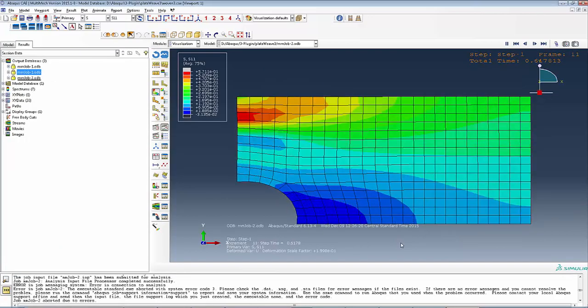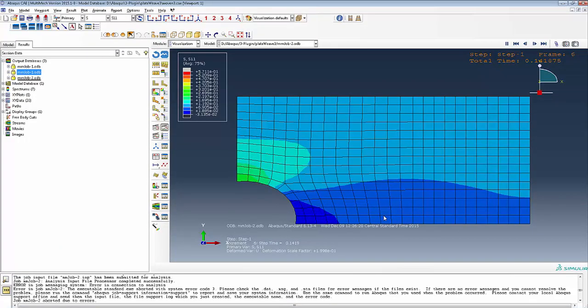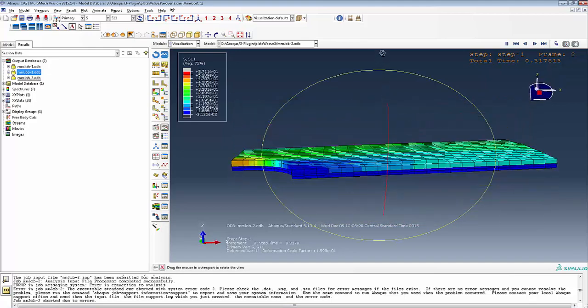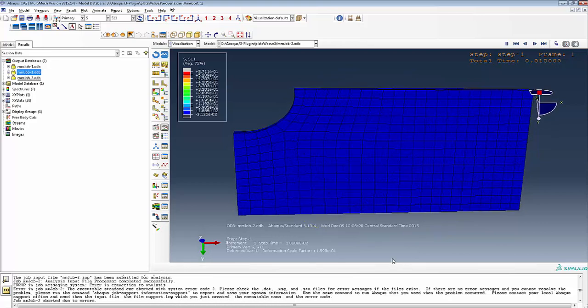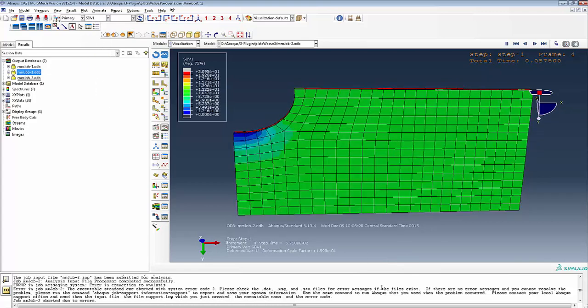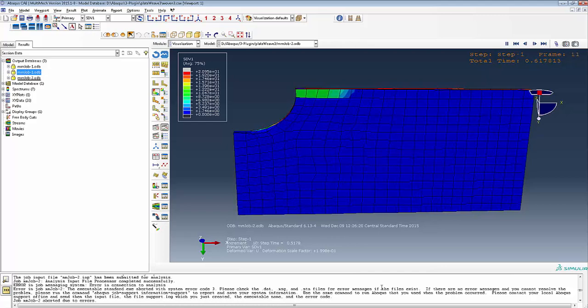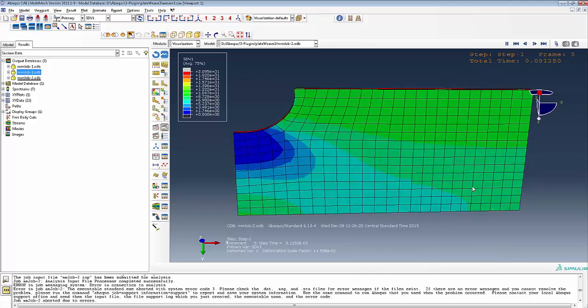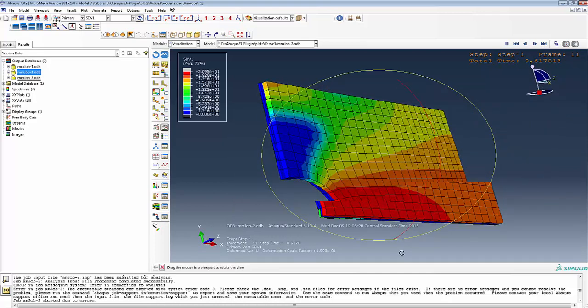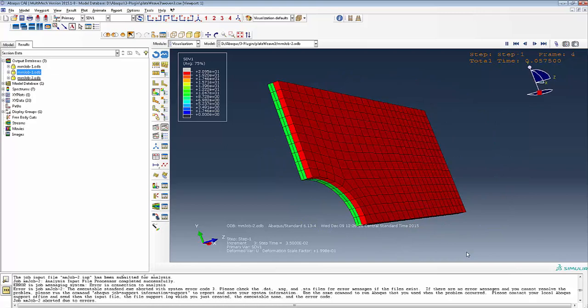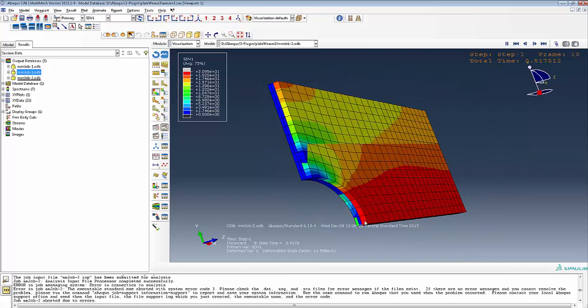So as expected, the upper layer carries most of the load within the part. The bottom layer is relatively unstressed because it fails so abruptly. You can hardly even see it, but if you look at the stiffness components that are output by Multi MEC, you can see it starts with an intermediate stiffness and then quickly fails throughout. That causes the upper layer to carry the load, and then failure starts to propagate throughout that top layer.